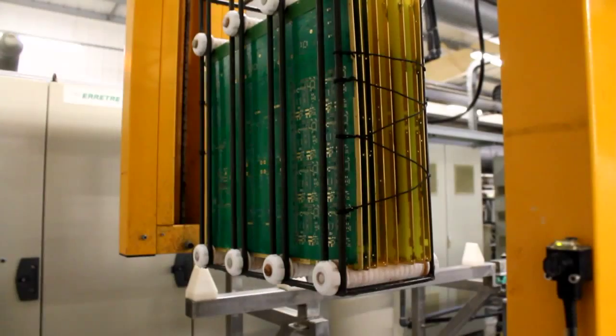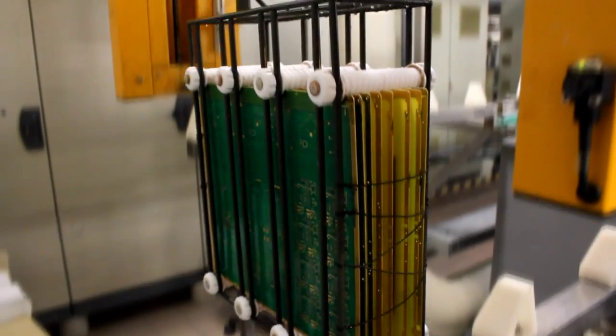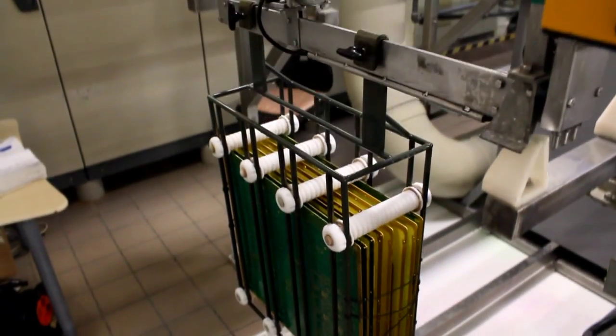The line is fully automated, moving the panels through a series of tanks which clean and sensitize the copper surface and then deposit about 5 microns of nickel and 1/10 of a micron of gold.